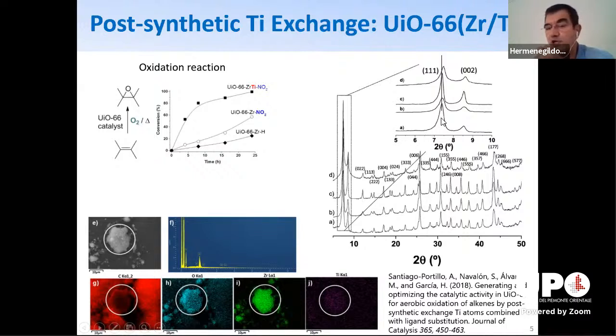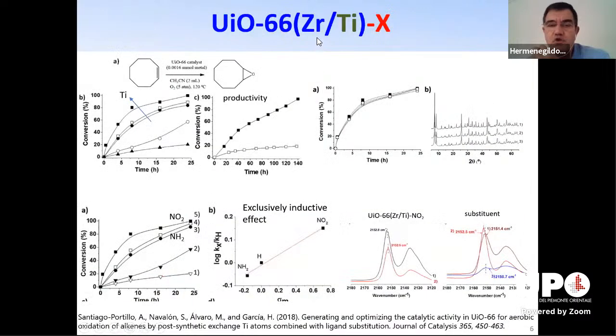For instance, when you move from pure zirconia and introduce higher amounts of titanium, there is a small but clear shift in the XRD, and this is because the size of titanium is smaller, so the position of the peak changes to higher angles. Of course, we also have the distribution of the metals, zirconium and titanium, and they coincide. This material containing zirconium and titanium, where we are also modulating the linker, can be used for oxidation with oxygen as oxidizing reagent. And for instance, we can form epoxides.